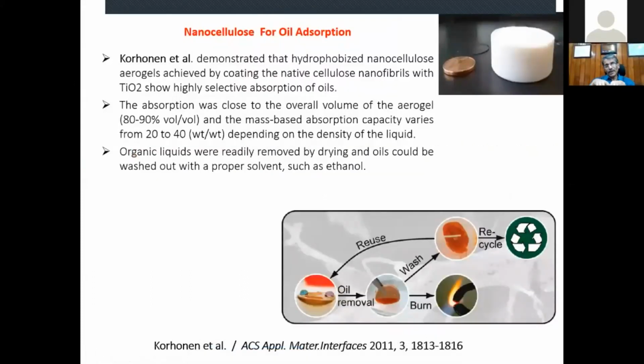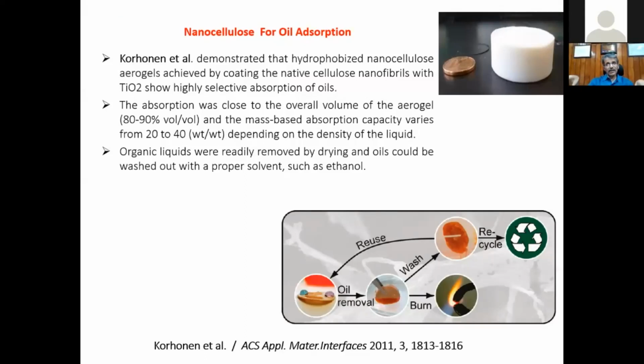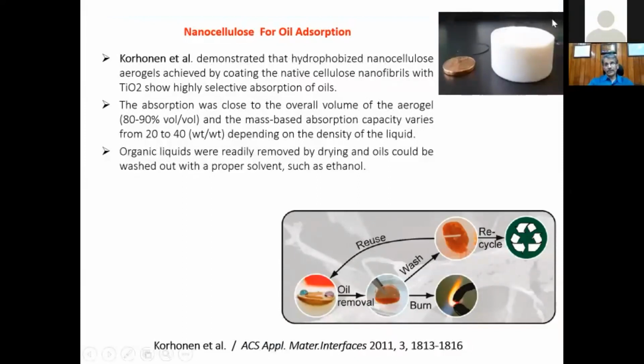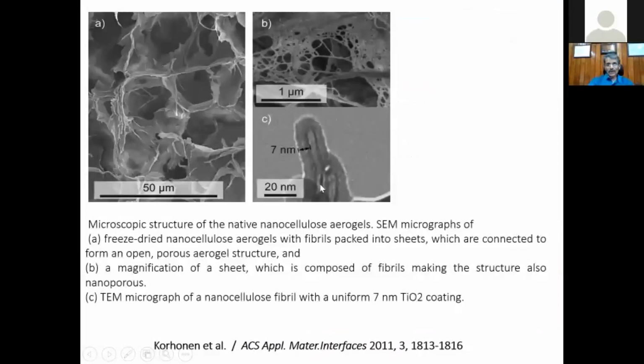Now let me show you some of the work done by the Finnish group. The Finnish group wanted to purify water in the sea. You all know that water in the sea is increasingly contaminated. Particularly from ships, we have lots of incidents where oil is leaked from the ship, or there will be several cases where ships sink in the sea. Therefore, we need to have methodologies to purify seawater. So what the Finnish group did is they made an aerogel of nanocellulose. And then they made the aerogel surface hydrophobic by a titanium dioxide coating.